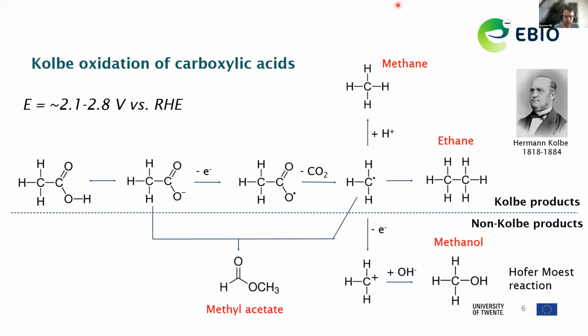But I have to point out that all of this has been so far reported or analyzed in batch reactors, and the product detection was rather based on the end of lifetime of the electrolysis. So there was not a continuous product selectivity detection reported so far in literature. And that's where we started off with our research, because we were really interested in whether there are any selectivity changes throughout electrolysis of acetic acid to either form ethane or the Hofer-Moest product methanol.